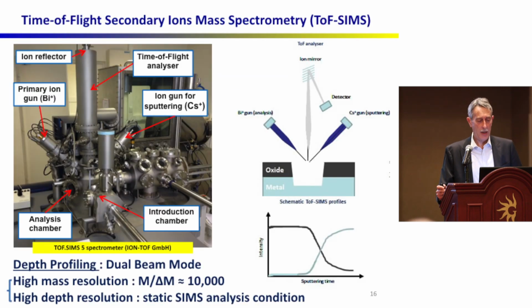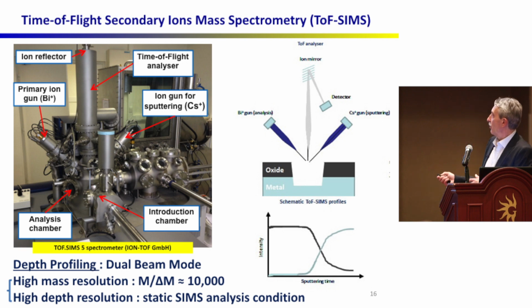To do that, we have used time-of-flight SIMS, which is a dual beam technique, so we can analyze with an extreme surface sensitivity. It's much more sensitive than XPS. We can analyze the surface with one beam. Ions are emitted in the time-of-flight spectrometer, so we can analyze the whole periodic table quasi-simultaneously, just looking at the time that ions take to fly in the analyzer. And with another beam, a cesium beam, we can make a depth profile.